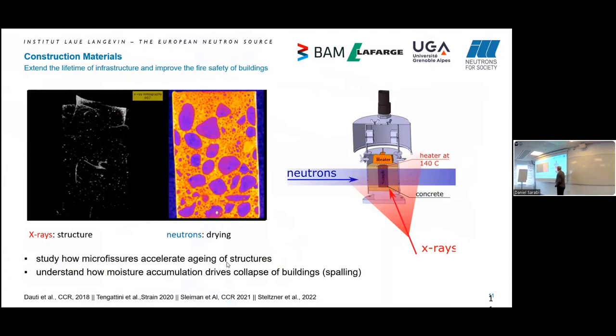But in this case, they looked at concrete drying or concrete under heat, which is important for a number of reasons. The structural integrity of concrete, but also, and I didn't know this until I spoke to the instrument scientist, apparently when a building catches fire, the concrete heats up, and if there's any water that's trapped within the concrete in a way that doesn't have a path outwards, there can be a huge buildup of steam that catastrophically releases at some stage, and concrete fails, and then the building collapses. So understanding the mechanism for concrete drying and what happens during heating is really important.